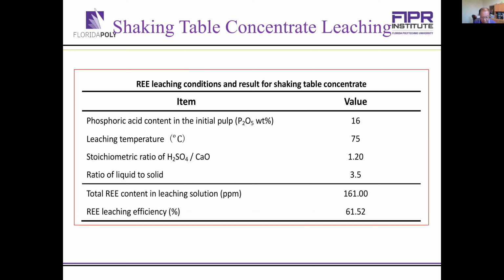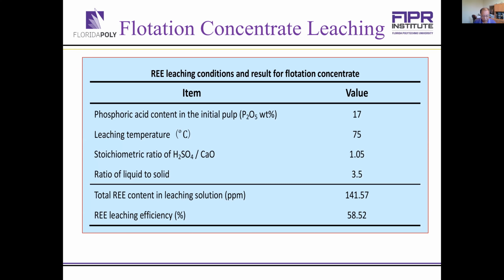The leaching test, we used the standard leaching process for manufacturing of sulfuric acid, phosphoric acid. We achieved 61% leaching efficiency. From the flotation concentrate, the recovery is about close to 60%.